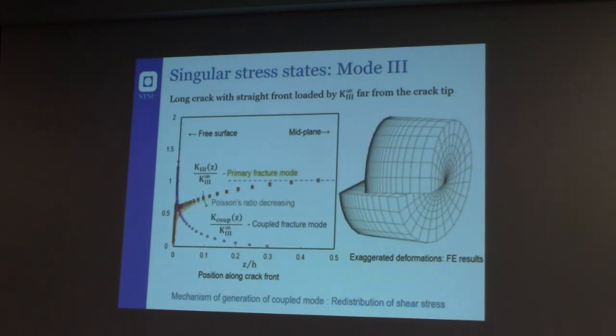And what we did later was to do the same. We apply, in this case, a nominal pure mode 3. And what we obtain is that the pure mode 3 is also transferring to the component a local mode 2. So actually, mode 2 and mode 3 are always coupled together and are generating some additional local mode 2 and mode 3 that are locally present close to the free surface of the component. And also in this case, the value of the local K2 induced, the coupled mode, was not negligible. It was a very high intensity with respect to the generating mode.